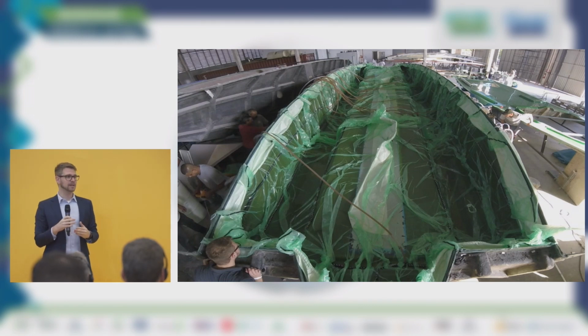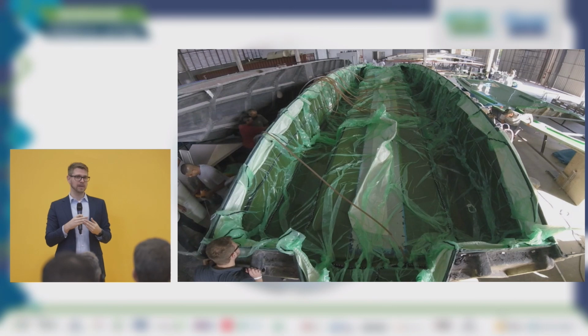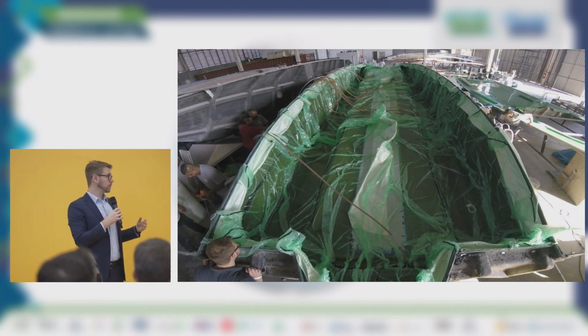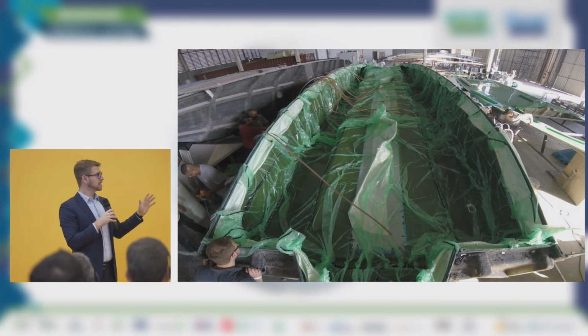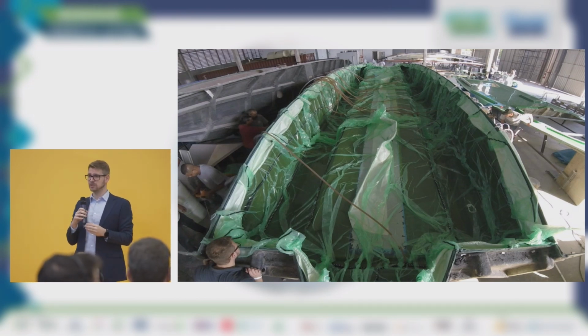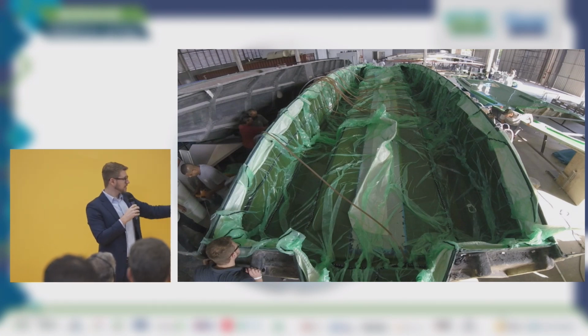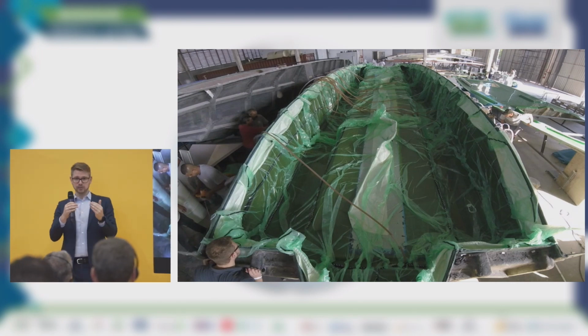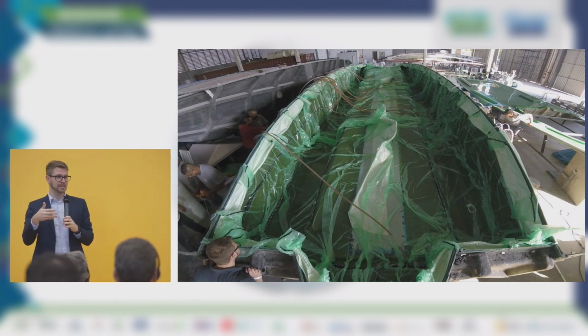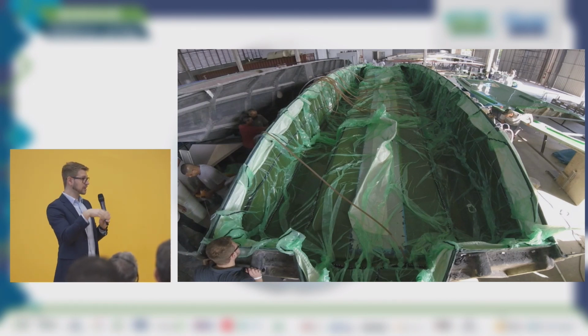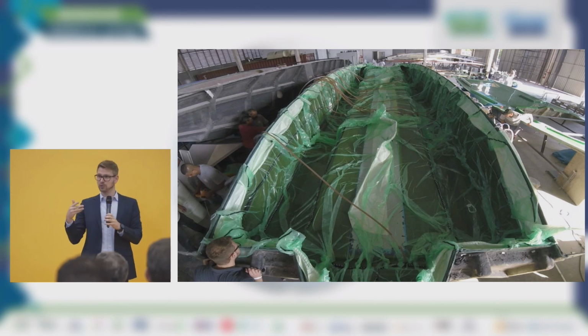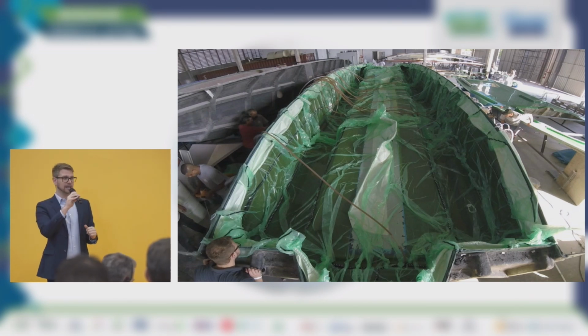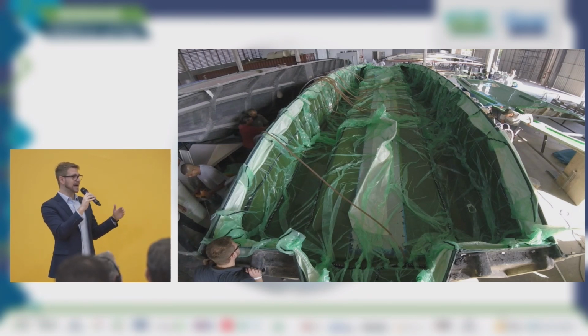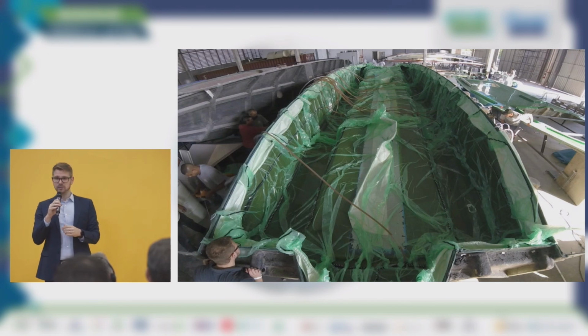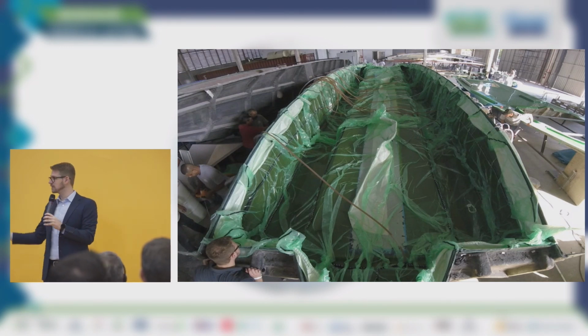We want to infuse the material very quickly. This is an infusion that had a gel time around 15 minutes. We have to control with some breaks these glass fiber layers to reduce permeability so that we don't pull a lot of resin to the trap, and then we have to feed with resin all the time. We can break this infusion as soon as it reaches 100%, and that's efficient, and the end result is very good.